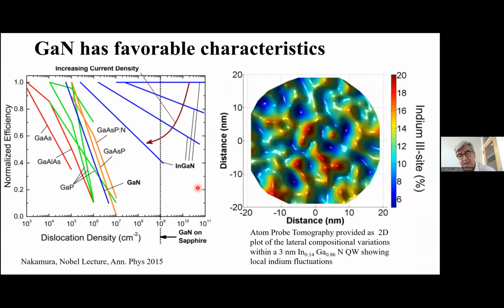Now, there were some interesting tricks about gallium nitride in terms of its performance and its susceptibility to dislocations. It was always known that every other material, including gallium nitride, would have a big decrease in efficiency of light emission at high dislocation density. So people had to be very careful to grow high-quality epitaxial layers. But gallium nitride, to get blue emission, has to be combined with indium gallium nitride quantum wells to get blue or green light emission, depending on the composition. And what was noticed right away was that there was no native substrate of gallium nitride in those days. So the layers were grown on sapphire with a very large lattice mismatch and led to a very high dislocation density. But those InGaN quantum wells still had relatively high efficiency, even at dislocation densities where it was not thought possible that a semiconductor light emitter could work.